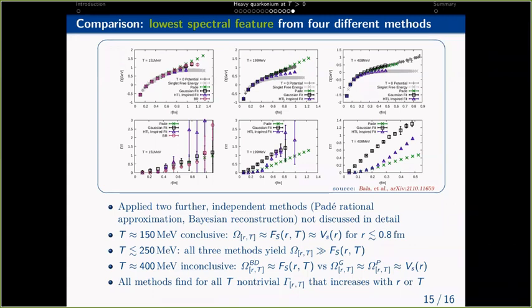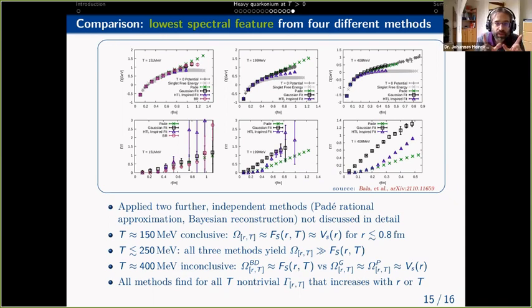Sure, I'm not surprised that there is a very large width corresponding to the imaginary part of the potential, but I'm quite surprised by your finding that there is almost no, or very weak, screening up to temperatures like 300 or 400 MeV. On the other hand, in the lattice results, including your current results, there is strong screening in the free energy that already occurs near TC, right?